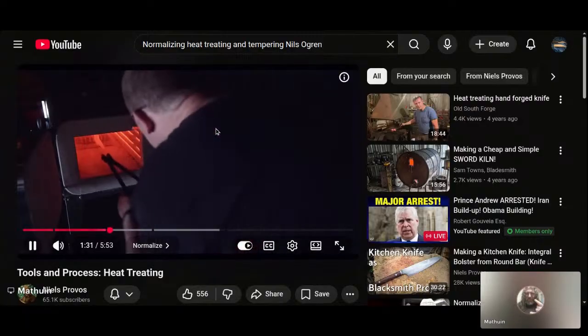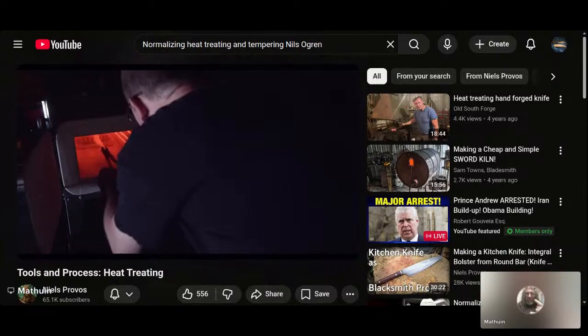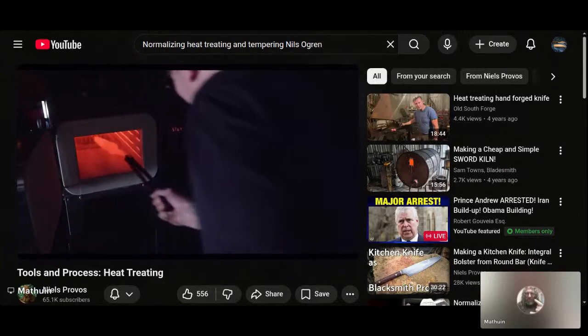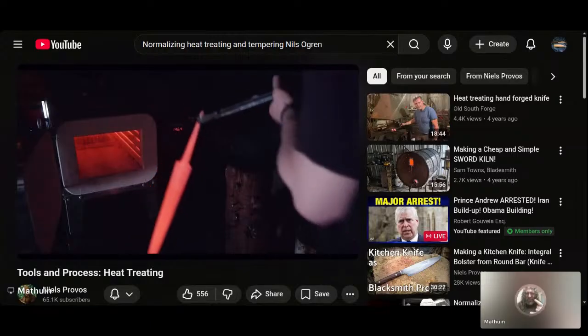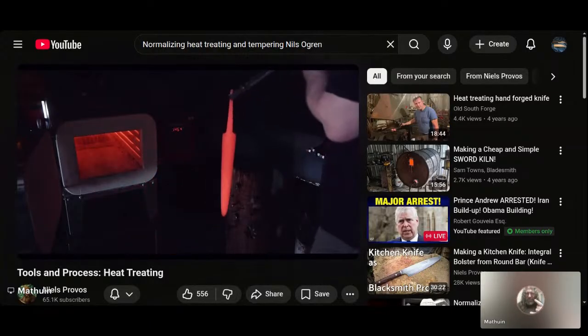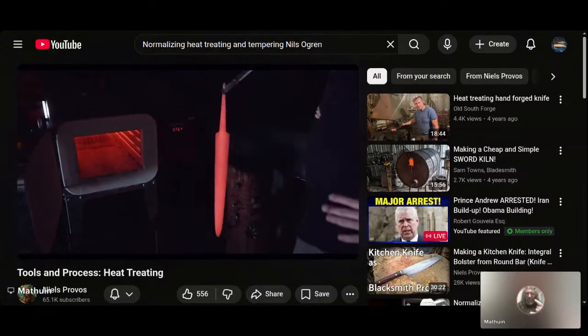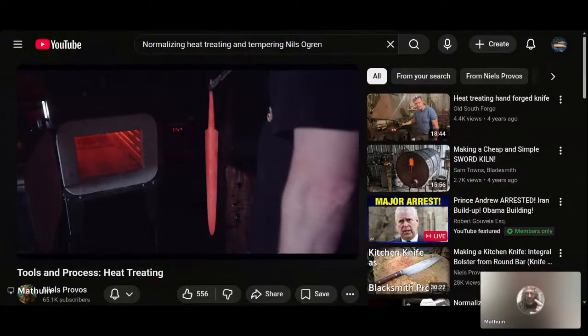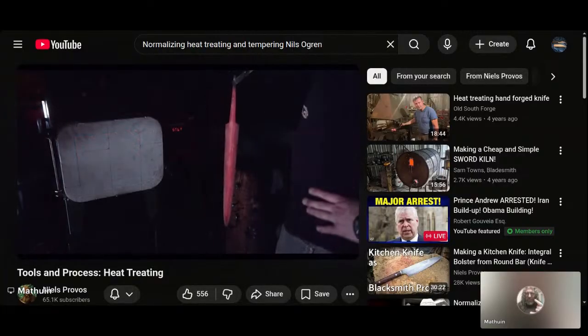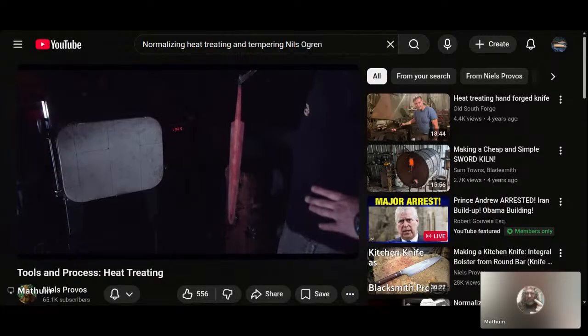Cooling from its critical temperature reduces the size of these grains. This is also a good opportunity to check for warping, which may occur when the bevels have been ground unevenly. I was also hoping to show you some recalescence, which happens right when the carbon in the iron matrix transitions from austenite to ferrite. That transition releases visible heat. You have to check my spear video where you can see that clearly. Here, I unfortunately stepped into the video.